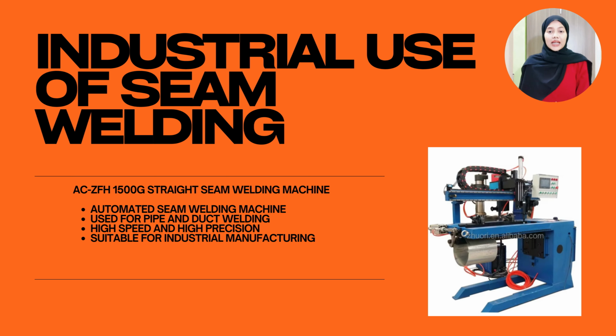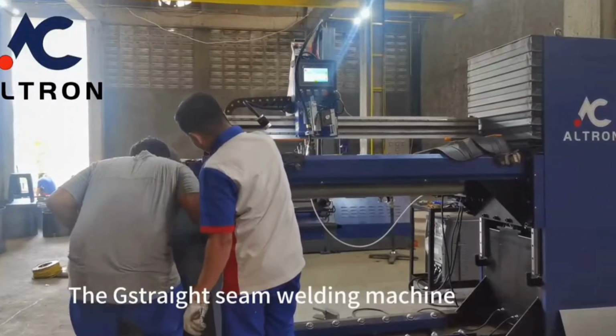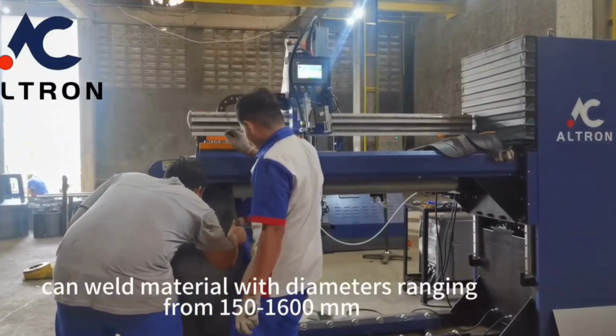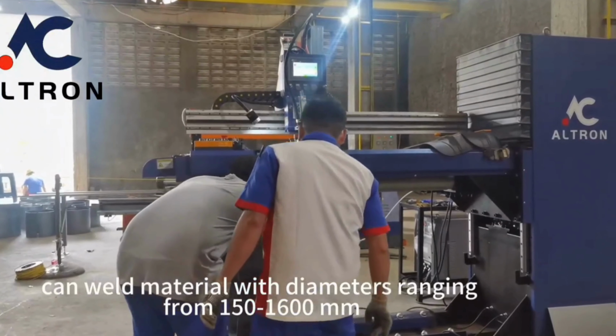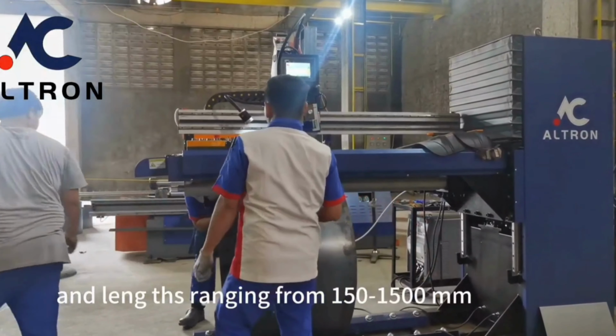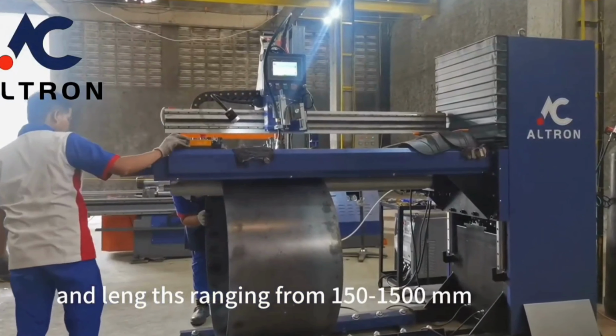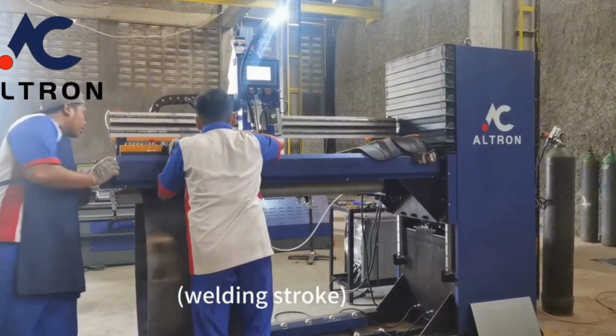This slide shows an industry application for seam welding using the ACZFH 1500G straight seam welding machine. This machine is fully automated and commonly used for pipe and ducting welding in industry. It offers high welding speed and good precision, and also improves production efficiency for industry application. The straight seam welding machine can weld material with diameters ranging from 150 to 1600 mm and lengths ranging from 150 to 1500 mm welding stroke.